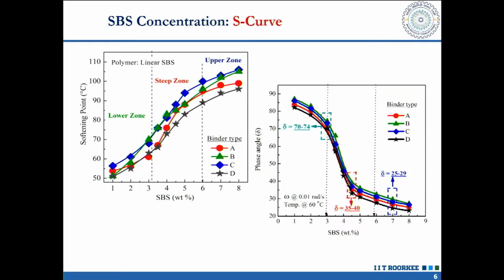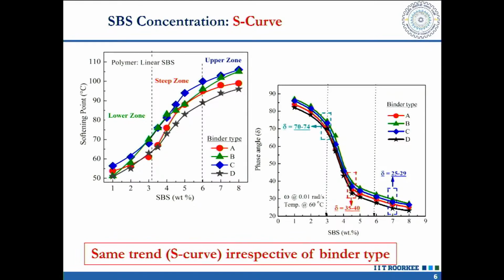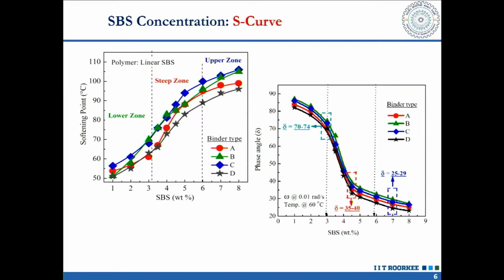After SBS concentration, I have tried different types of bitumen obtained from different sources. When you modify bitumen obtained from different sources, we don't see any significant difference among the different bitumen types, majorly because the concentration effect is more dominating compared to bitumen type. This can be observed from the phase angle also. Phase angle is the data obtained from the rheological analysis of PMB.